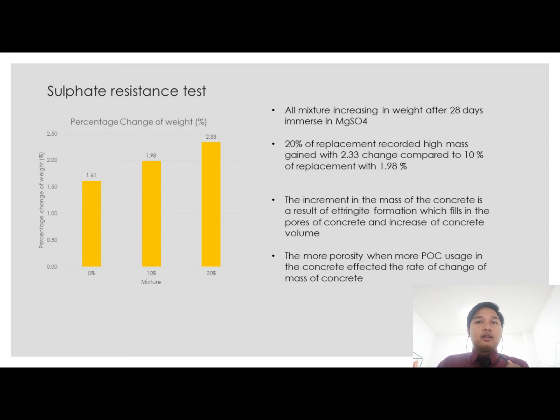The increment in the mass of the concrete is a result of ettringite formation which fills in the pores of concrete and increases the concrete volume. The more porosity when more POC is used in the concrete affected the rate of change of the mass. We can see the normal concrete shows a lower percentage of weight change compared to the palm oil clinker replacement.